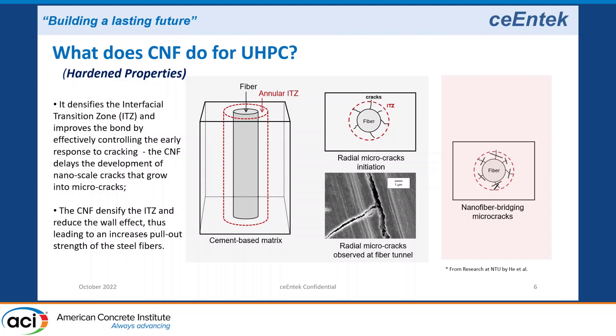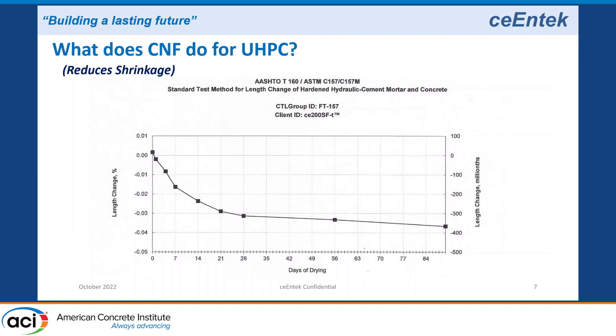All cracks originate at the nano molecular or nano scale. As the concrete is put into tension, the nanofibers bridge the nano cracking, delaying the onset of nano cracks which grow into micro and eventually macro cracks. This increases the first crack modulus of rupture with carbon nanofiber in the matrix. Since you're also increasing the bond to the microfiber, you increase the ultimate tensile capacity.